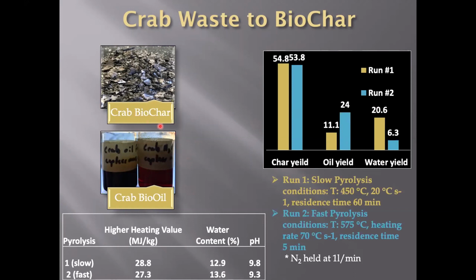So most of the work done in the area of biofuel has focused on using woody biomass as the starting biomass to produce the bio-oil and using fast pyrolysis. And woody biomass, especially woody biomass from softwoods, generates an oil product that has a higher heating value. So it's basically the gross energy of the oil of about 17 megajoules per kilogram. Now, compare that to what is currently used as bunker fuel. So most bunker fuels from fossil fuels will have higher heating values of around 40 megajoules per kilogram. The crab bio-oil is closer to bunker fuel, around 30 megajoules per kilogram. And this is really promising, and we are excited by this.